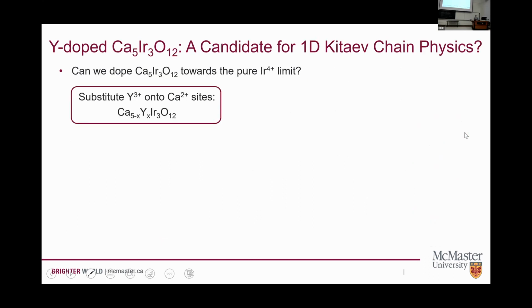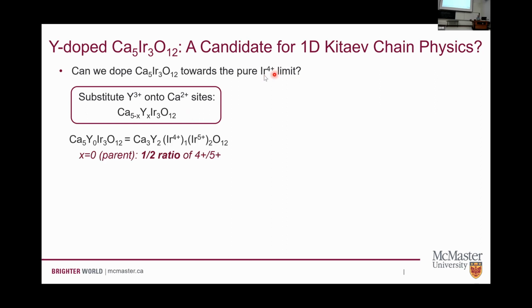So what Z did, actually a suggestion from John Greedon, who is seen in the audience here, was to dope this system to try and bring it from this mixed valence back towards the ideal 4+ state. So we did this by trying to incorporate yttrium into the structure. So putting yttrium, which is 3+, onto the calcium, which is 2+, to try and get towards this all quantum spin state again. And so we start out here at x = 0, this parent compound, where again, we've got 1 to 2, iridium 4+ to 5+.